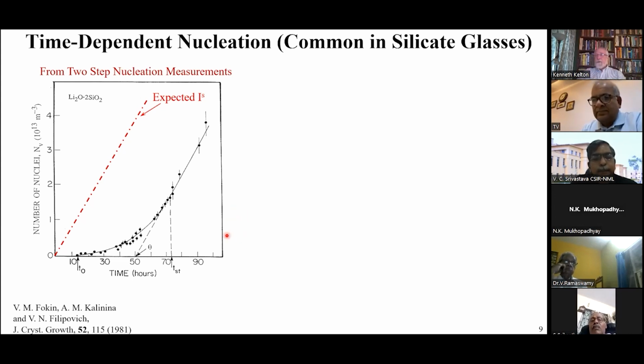Then you just count the number of nuclei that are present after the second treatment. If you looked at the number of nuclei as a function of time, what you would expect from Becker-Döring is to get something like this. This would be the expected steady state nucleation rate. The numbers should increase linearly with time since the nucleation rate is constant. But instead, what you find is that very often the nucleation rate, which is given by the slope, becomes very small initially, and it increases with increasing time. This is nucleation time at the first treatment, the nucleation treatment, and eventually becomes steady state.